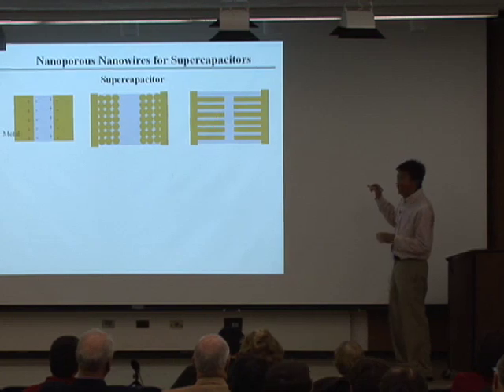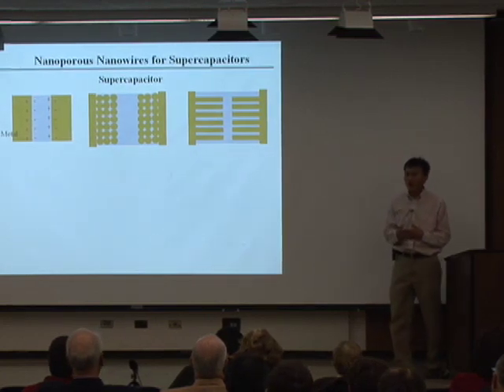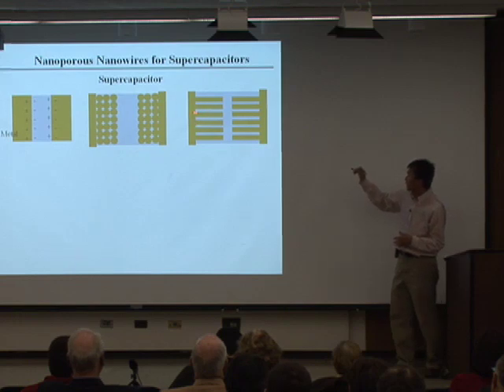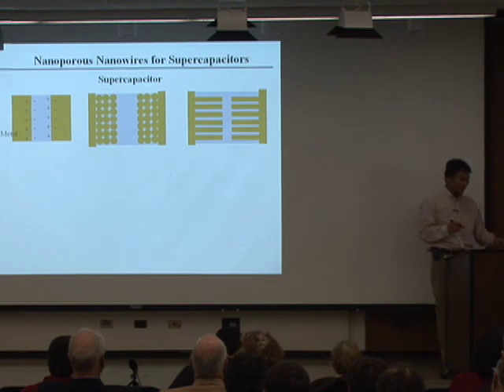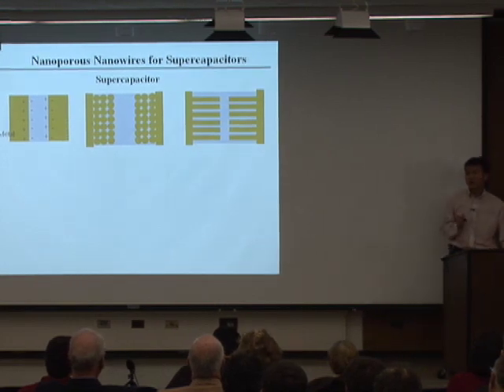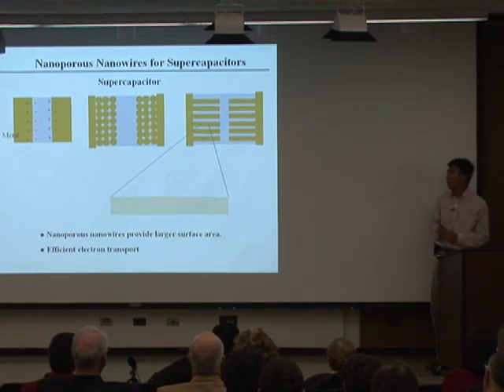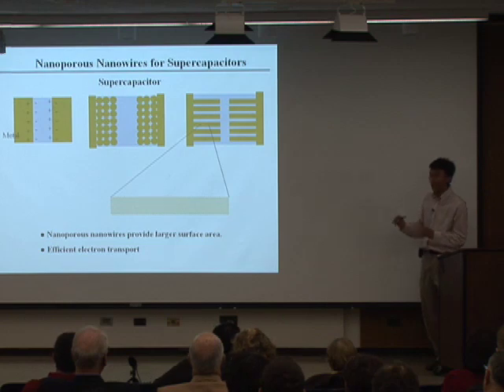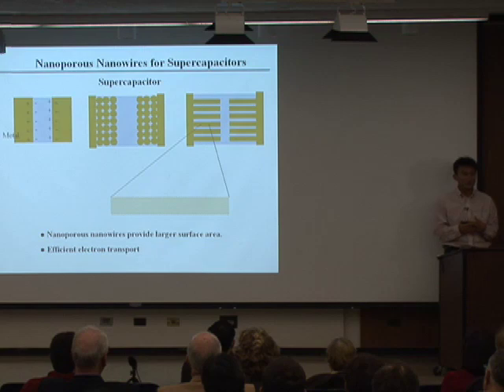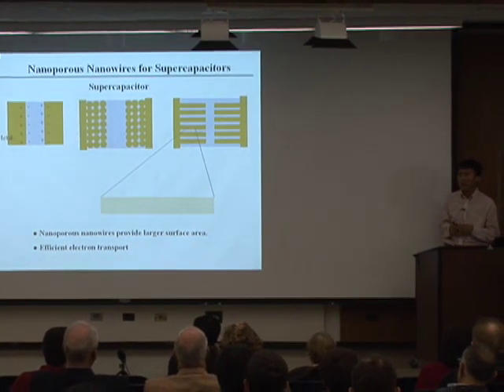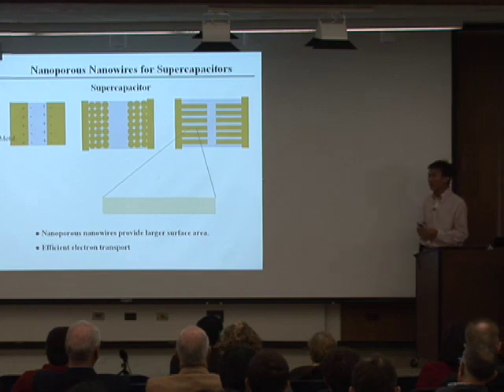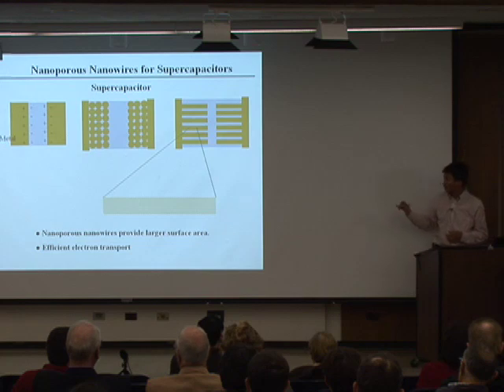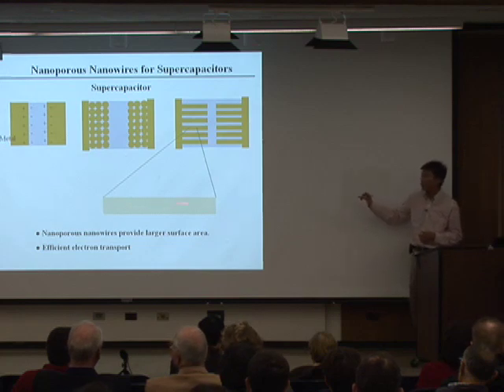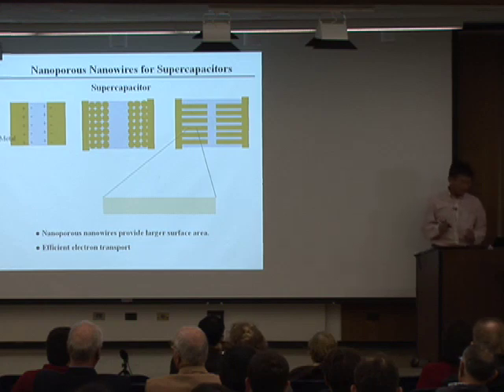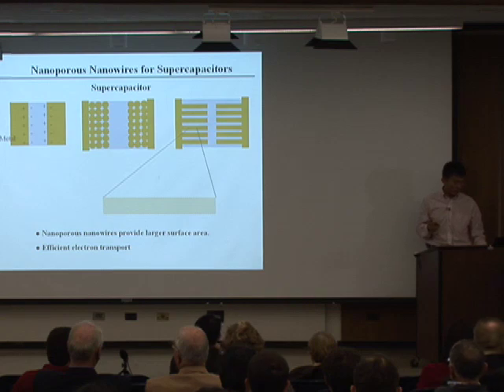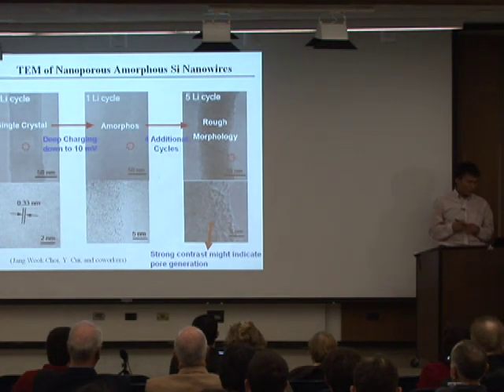So I said using nanowire can be beneficial for supercapacitors because you increase the surface areas, you have efficient electron transport. Now having these nanoporous nanowires for supercapacitors is going to be even better. Now you have a lot of these pores. This creates additional surface areas to increase your capacitance and to increase your energy density of supercapacitors. And at the same time, they are well connected. All these materials are well connected, so they still provide efficient electron transport pathway. So we decided to explore this idea.